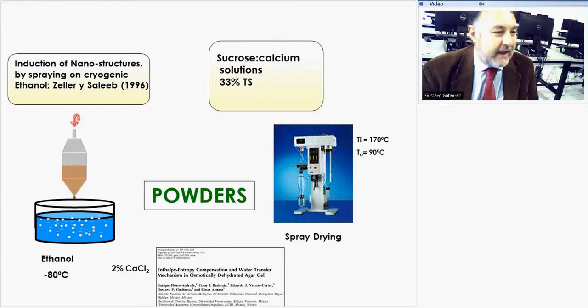In a nanoscale by spraying on a cryogenic bath at almost minus 80 degrees Celsius, she sprayed this solution followed by calcium chloride, and yield around 33% of total solids. And on the other hand, we have to spray dry that. So here we will do a freeze drying, whereas here we were only able to process our material by spray drying.